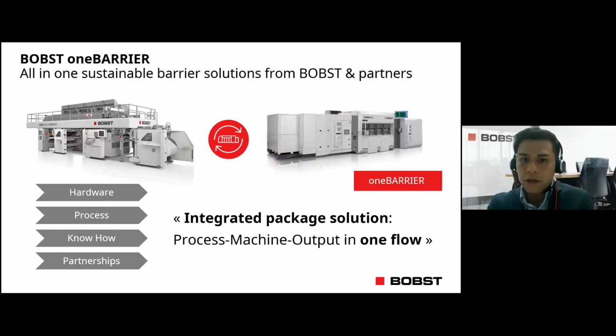On the left is the Vision D850 coating laminating machine, which is used for applying the primer and of course can be used for lamination, where we leverage our know-how of inline corona treaters to improve the surface energy of the film, a gravure coating station, which can work in both forward and reverse for uniform and flawless coating. Our drying technology is second to none, as we utilize hybrid drying technology with double-sided airflow for fast evaporation, which is favorable to counter the tendency for PE to extend under heat load conditions. BOBST is also well known in the market cross-platform in handling web tension capabilities, which is crucial when handling PE.